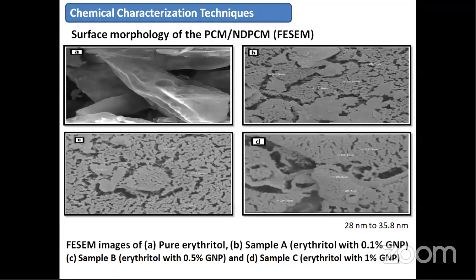the surface morphology of PCM or NDPCM, the microstructure or morphology of erythritol with the 0.1%, 0.5%, and 1% graphene samples were investigated by field emission scanning electron microscopic analysis. The size of the nanoparticles in the samples was found to be 28 nanometer to 35.8 nanometer. Some images showed that the graphene nanoparticles were randomly distributed and held the nanoparticles in fixed positions.